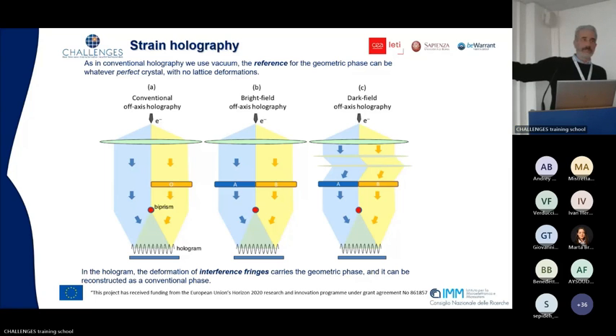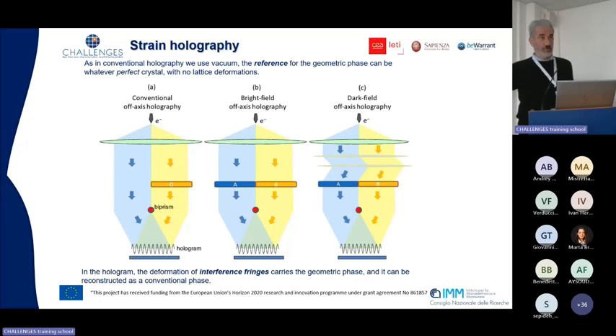You illuminate our sample. There is a hole close to it; when you thin the sample, you can easily obtain a hole in which the electron can pass through, and another electron can pass through the object. Then a biprism deviates the two electrons, making them interfere in the final hologram. In bright field off-axis holography, we can position the sample so that here we have the reference material, let's say the silicon substrate in our case, and here the silicon germanium strained material, and make the two waves interfere.